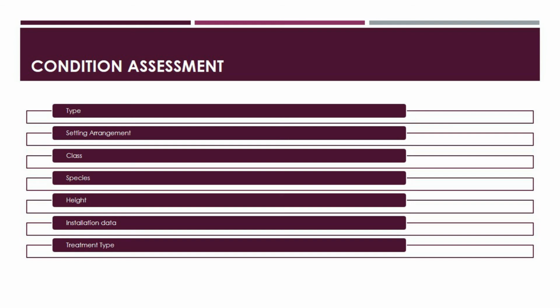Direct measurements, which are things such as external rot or shell thickness, are taken at 3 points around the circle at or just above ground level in the case of wood poles. The thickness of the shell is measured to the nearest half inch, while the thickness of the outside rot is measured to the quarter inch.